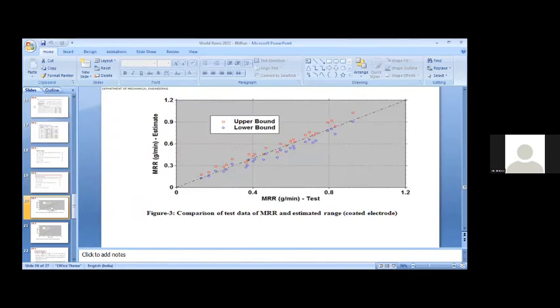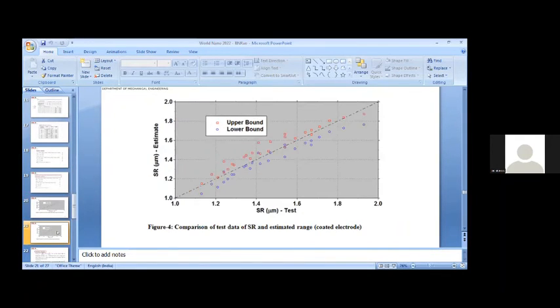Then if you see the next few graphs, here also they have conducted the experiments. The complete experimental data versus the lower bound and upper bound: the experimental data is in between or close to the lower and upper bound predictions. So this is the surface roughness for the coated electrodes.